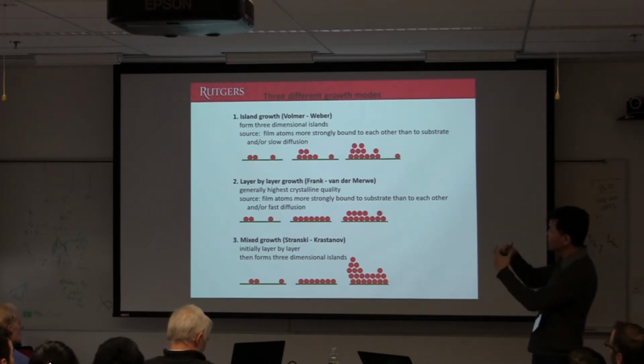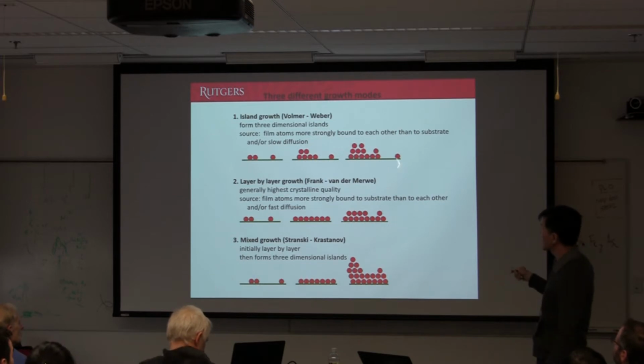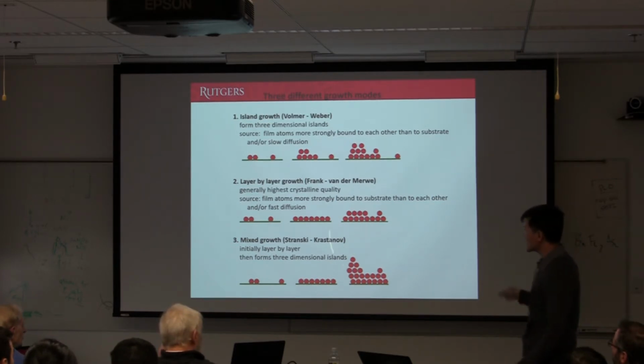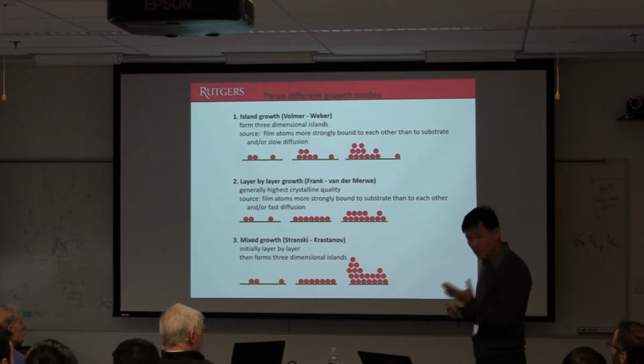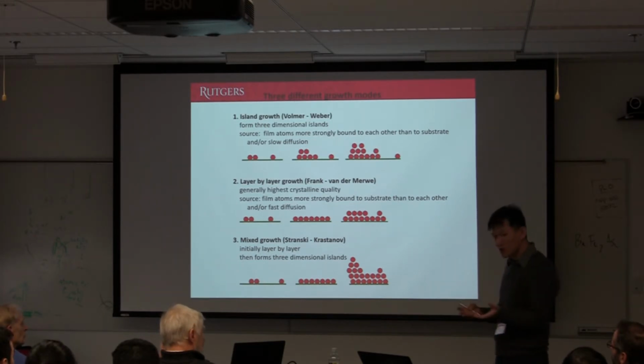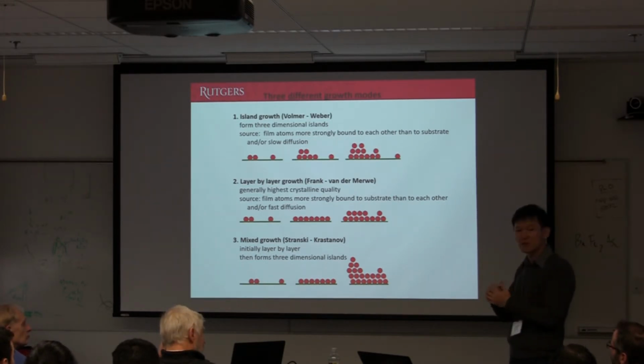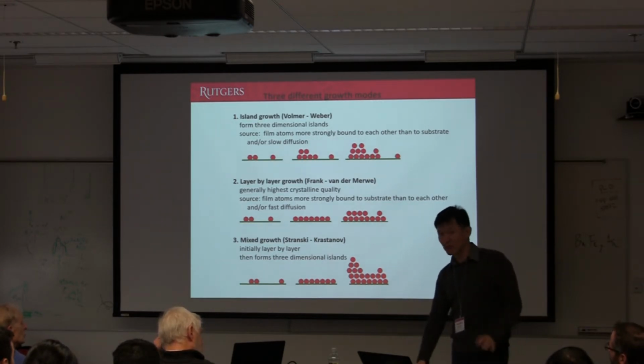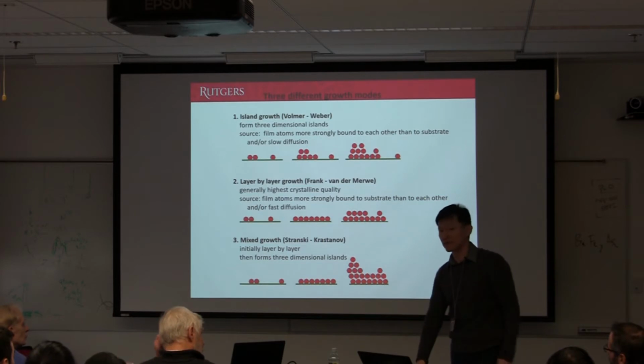factor between the substrate and the film, sometimes the film grows in 3D mode, or sometimes it can grow in 2D mode, or sometimes it can grow in an intermediate range. But this whole thing is affected by multiple factors, temperature and also reactivity with the substrate, and so by understanding these multiple factors, you can control all these three, and then you can achieve the morphology you want.